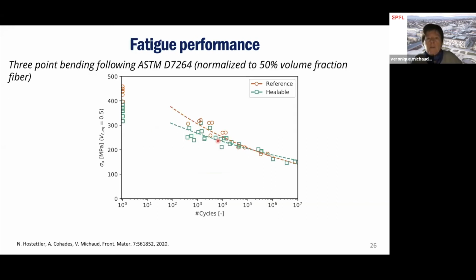Then we looked at the fatigue performance of the systems, because we suspected that if our material can heal small cracks, it should be able to heal fatigue cracks. So we did a 3-point bending fatigue test, normalized to 50 volume fraction fiber, presented here, where you have the SN curve. This is the virgin material. So our healable material is a little bit lower in property, as expected, than the reference material. However, we see that with the number of cycles increasing, there is a crossover, and the healable material becomes quite a bit better at high number of cycles than the reference material.